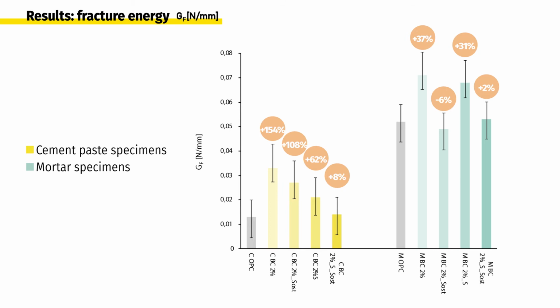Regarding the fracture energy, the results of cement-based specimens show an improvement of up to 150% compared to pure cement, in the case where the biochar was used mixed in water. The most encouraging results are the cases where the cement was substituted, obtaining more than 108% increase in the case where 2% of biochar was used mixed in water and dry with the dry powder respectively. In the mortars, the graph showed an increase of 37 and 31% compared to the reference specimens, in cases where biochar was mixed in water and in dry matter respectively.